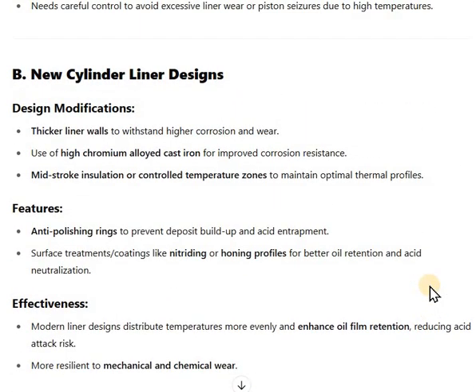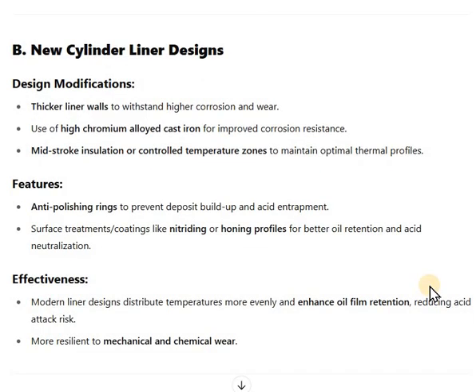New cylinder liner design: thicker liner wall to withstand higher corrosion wear. Use of high chromium alloyed cast iron for improving corrosion resistance. Mid-stroke insulation or controlled temperature zones to maintain optimal thermal profile. Features: anti-polishing rings to prevent deposits built up and acid entrapment. Surface treatment coating like nitriding and honing profiles for better oil retention and acid neutralization.